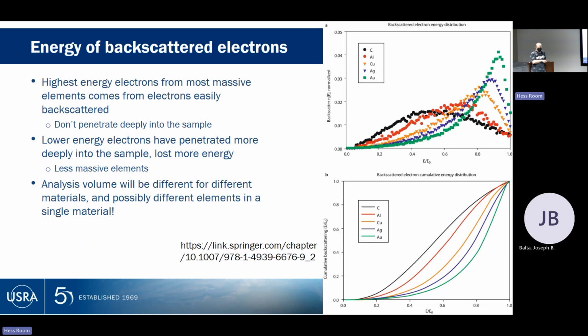We had a gold-coated sample in the room. Why is it difficult to get backscatter signal out of a gold-coated sample, even if the gold is only tens of nanometers thick? Because high mass elements like gold are extremely efficient at producing a backscatter signal. So even though we're penetrating the gold with some of our electrons, the gold, compared to carbon at the same thickness, is far more efficient at generating a backscatter signal.